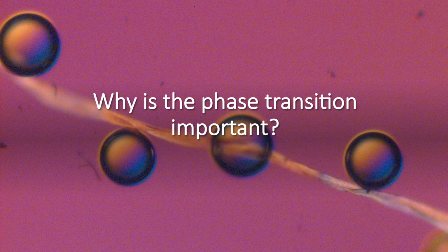But if we add an extra amount of sulfuric acid, the route of phases will be changed, and particles, instead of self-assembling, will aggregate. In this system, they don't show colors anymore, but at the same time, the viscosity of the obtained material will increase. So, why is the phase transition important? Depending on the path chosen during the chemical modification, we get CNCs which are trapped at different phase transitions. And this will result in the final properties that can be considered later on by the industry.